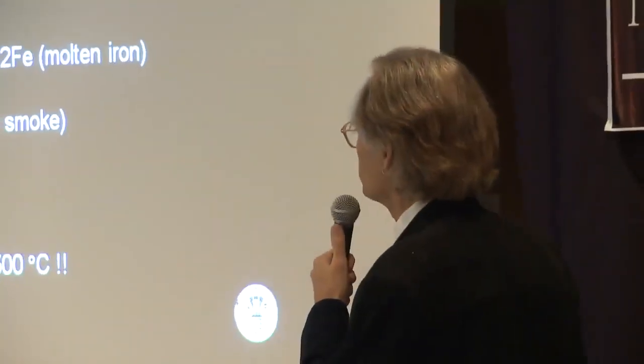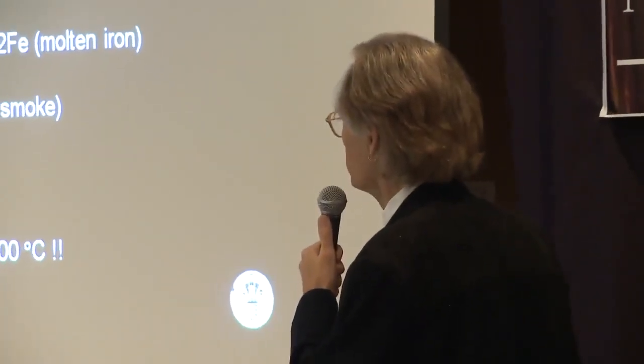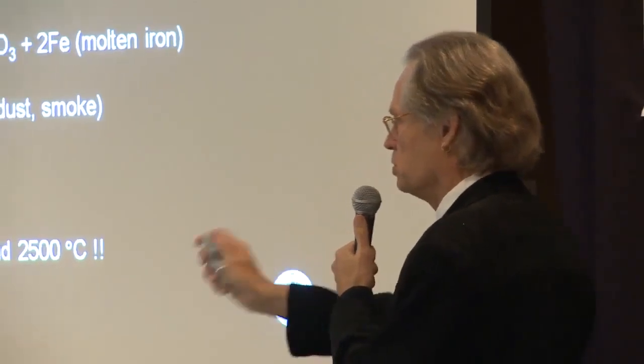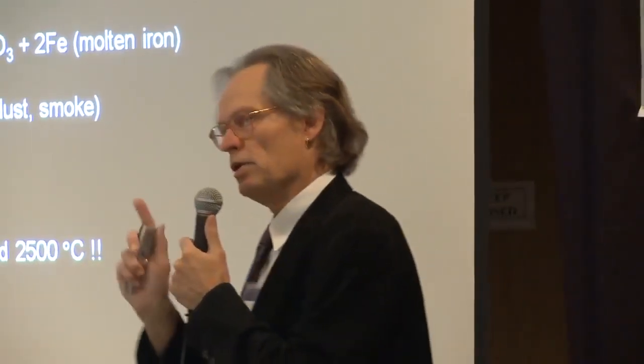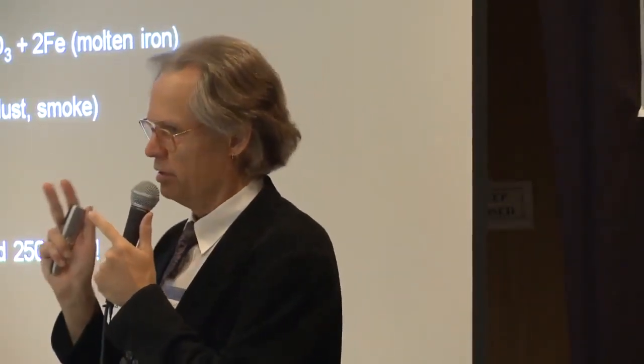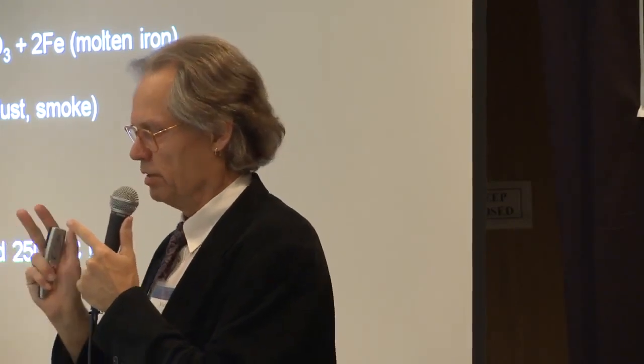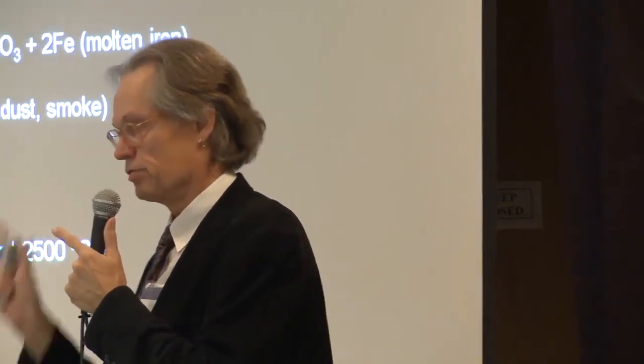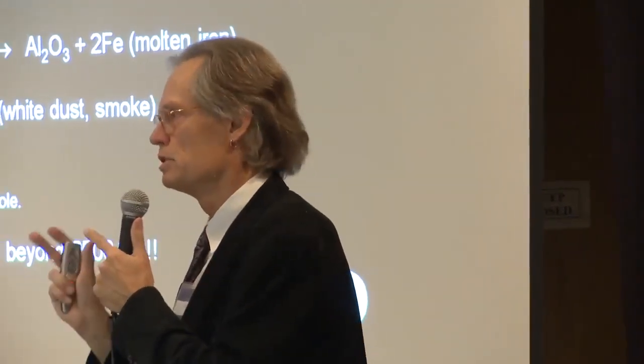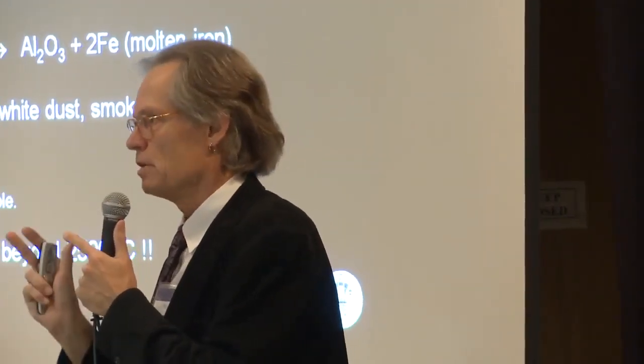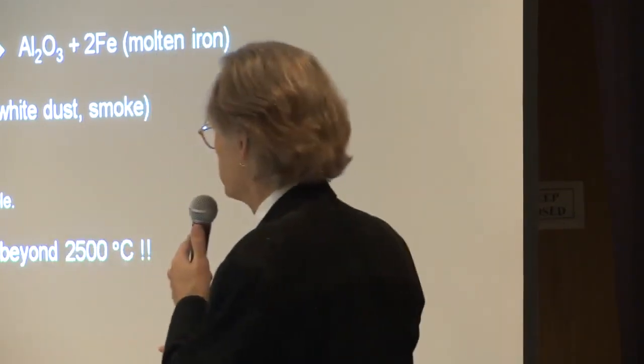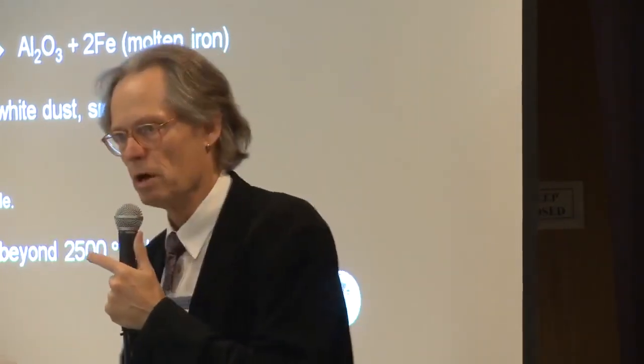Now, it can also be used to destroy things, which we have seen Jonathan Cole demonstrating so nicely. And this is the reaction which you would expect. Notice that in the red-gray chips there is iron oxide. We have seen this from the energy dispersive spectroscopy, and we have a good reason to expect elemental aluminum to be present. So we wonder what happens when you heat them up.